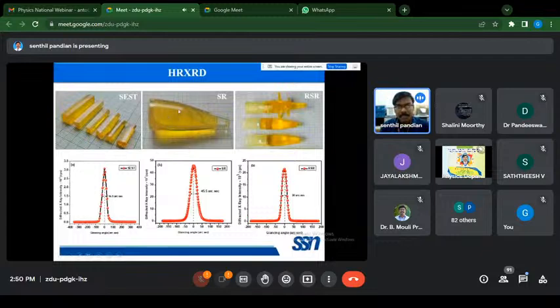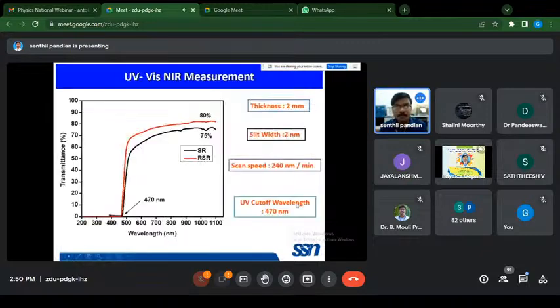But some impurities appeared in the SR method grown crystal. In order to avoid this, we have modified the SR method. This is the RSR method. Here we can minimize the impurity segregation in the RSR method. You see the crystalline perfection of the RSR method grown crystal is 30 arc seconds, compared to the SR and conventional grown crystal, it is very low.